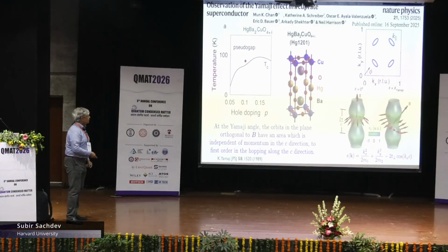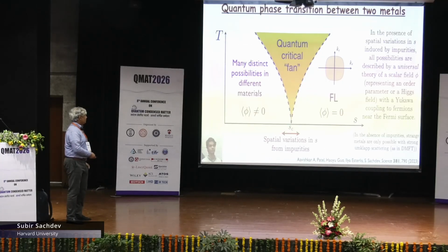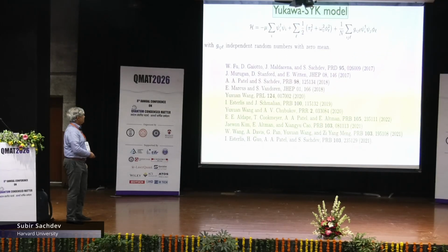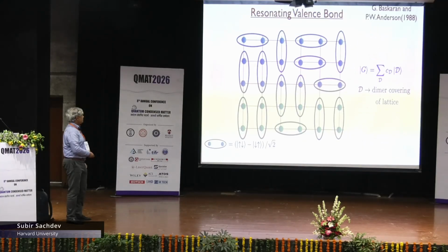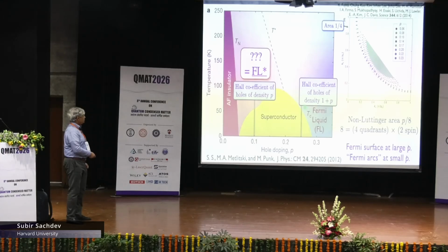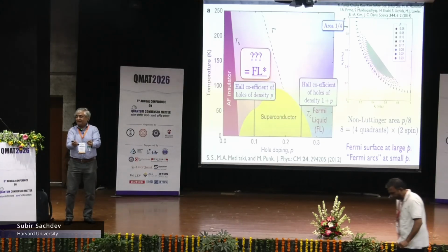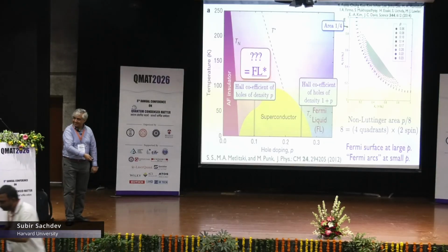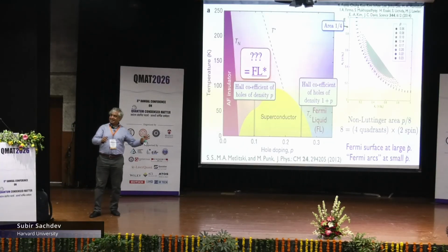But the difference between the superconductor here and the charge density wave, where is the phase diagram? Yeah, so the superconductor here and the superconductor here are the same. The charge density wave here is also fairly conventional, but the normal state here and the normal state here are totally different. So it's the onset of superconductivity that's different. The superconductor itself is pretty much the same, except when you open it up by looking at a vortex. Then it's different. And all of this, we have computed in many different papers.